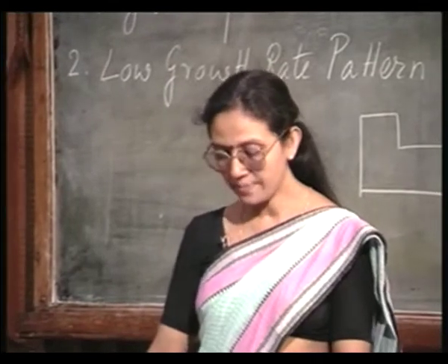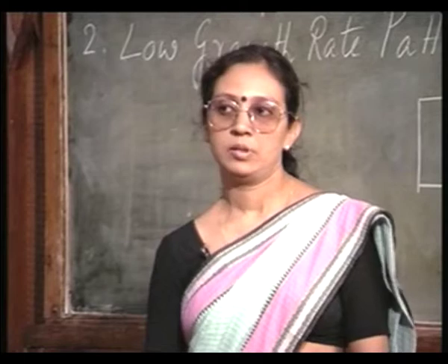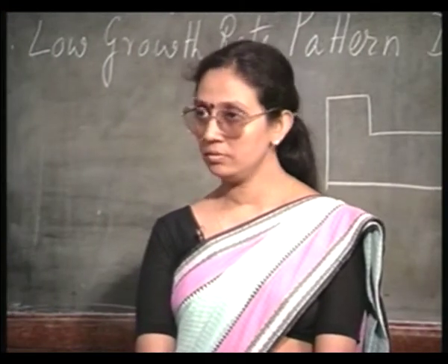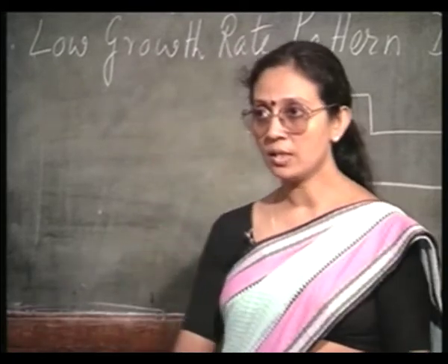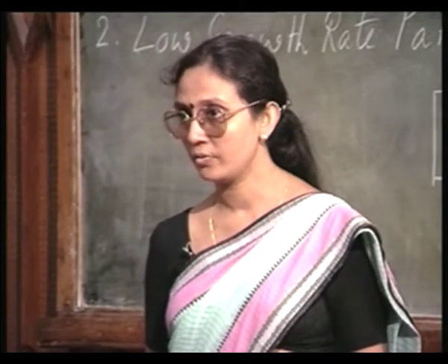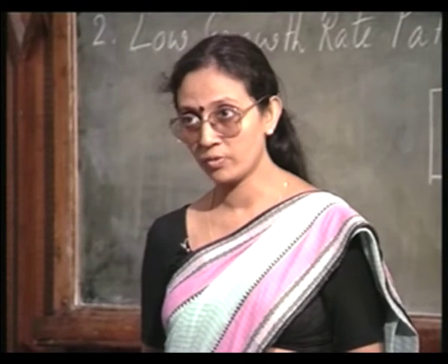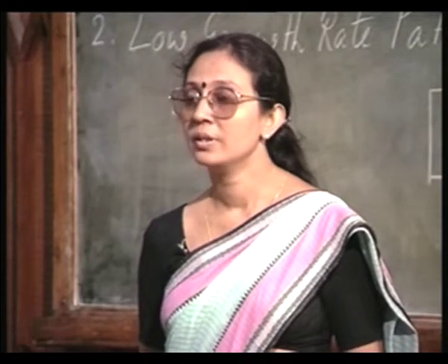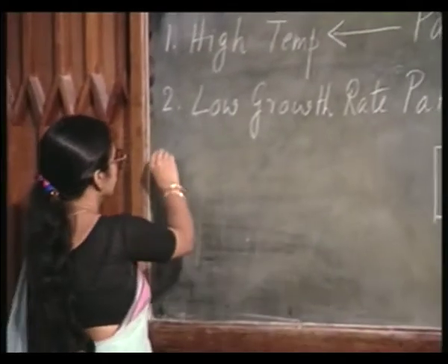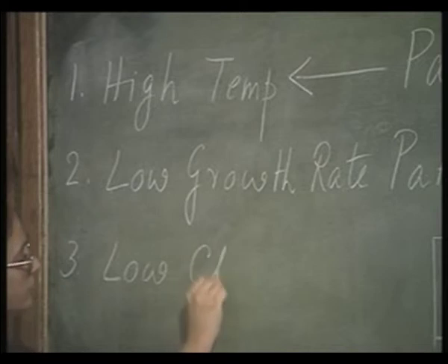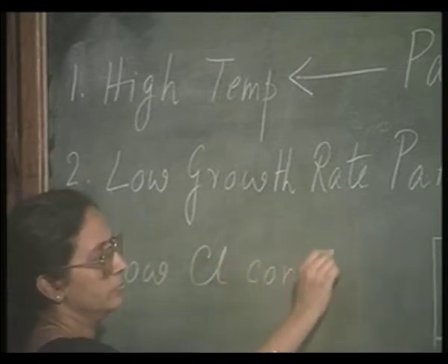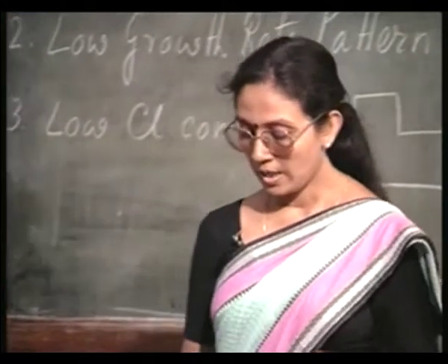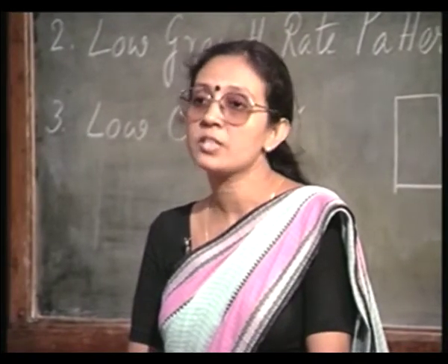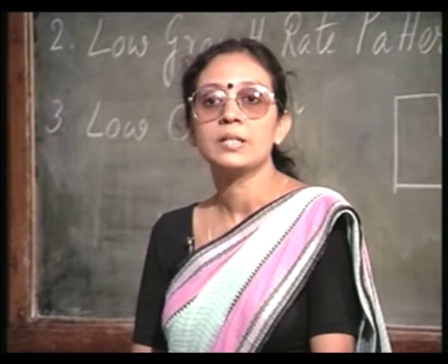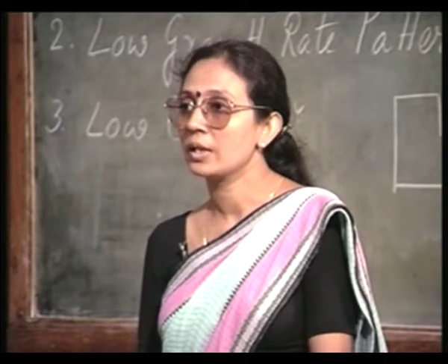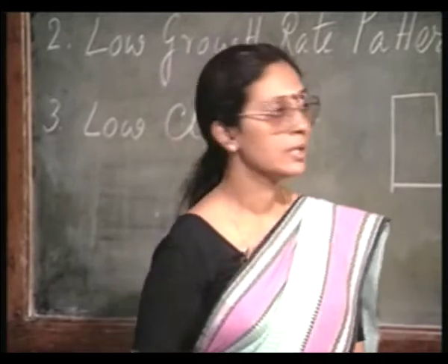And it is also seen that the more the amount of chlorine you have, the more is the pattern shift. Again it can be related, you see, the more amount of chlorine you have, the growth rate tends to be high, therefore anisotropy tends to be more, therefore reduce the amount of chlorine and you are going to have lesser problem of pattern shift. A corollary of this third point is that with lower pressure the pattern shift will be less. If you have lower pressure, you can vent out the chlorine or the HCl faster. Therefore, the pattern shift will be less.